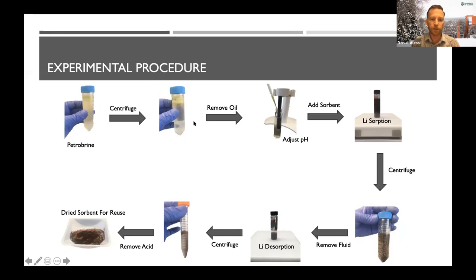So the first thing we do is centrifuge it, and you can see it's much clearer here, just to remove the solids, because we don't want those going into our DLE material and messing things up. Then we also physically remove the oil from the top, and we're left with a fairly pure solution. The pH is adjusted, and the reason for that is there's an optimal pH, depending on the brine, at which the DLE sorbent recovers lithium from the brine. So we did experiments across a broad range of pHs, but I'll show you the optimal pH in a bit. Essentially we adjusted to that pH.